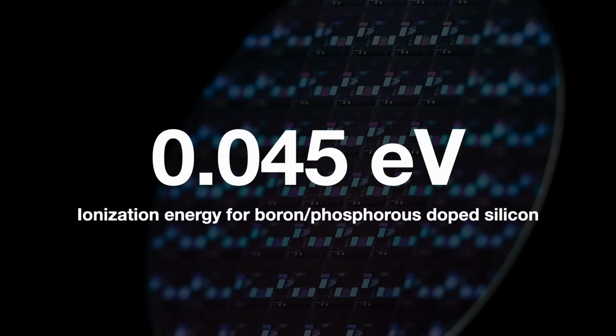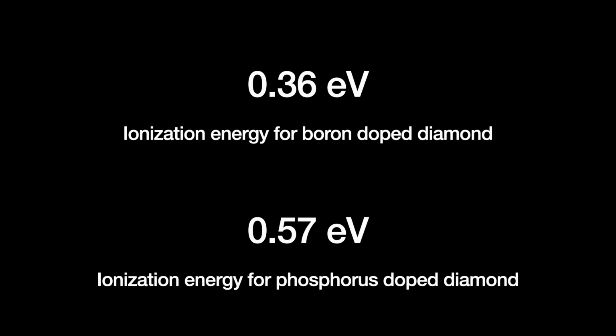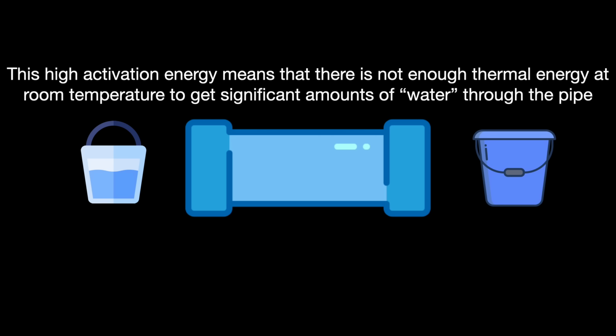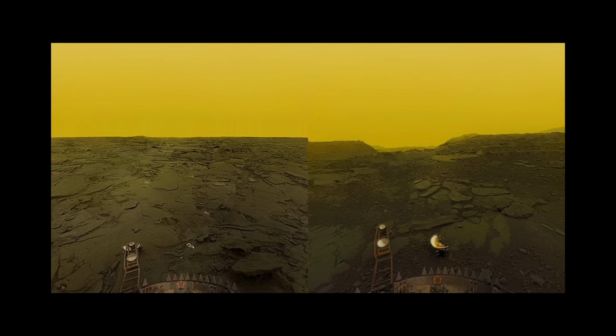But the threshold for doped diamond is multiples higher. Like I said, the correct lingo is to say deeper. Boron's is 0.36 electron volts, and phosphorus's is even deeper at 0.57. Thus, at room temperature, only a small percentage of the boron atoms give up their charge carriers. And so, unless a diamond transistor is subjected to high temperatures, you get too few charge carriers for the transistor to run efficiently. This is great if we want to run our diamond transistor computer on the surface of Venus, and it legit might perform really well there, but we're talking about Earth.